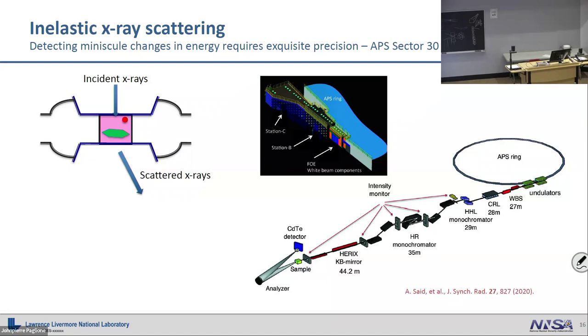It's very good at doing phonons. So that's something that's coupling. X-rays and neutrons are coupling equally well. You can do magnetic measurements on this too. There's a version of this that sits next door at a different hutch called MERIX, which basically does the magnetic version. So in that case, the big difference is with neutrons, you're naturally coupling to the magnetism because the neutron has a spin. In the X-ray world, you have to resonantly tune your energy to the magnetic atom that you have. Fortunately, at a synchrotron, you can do that.